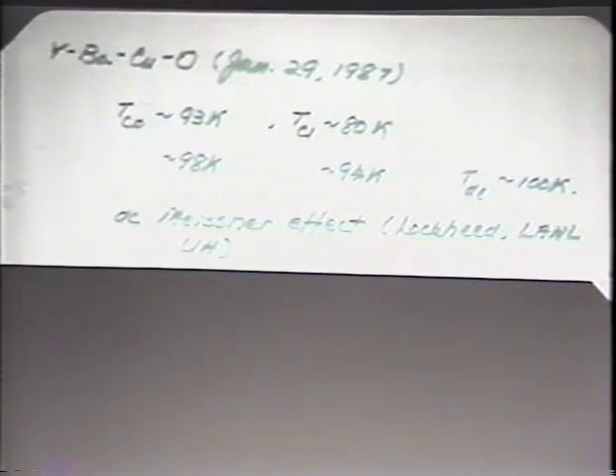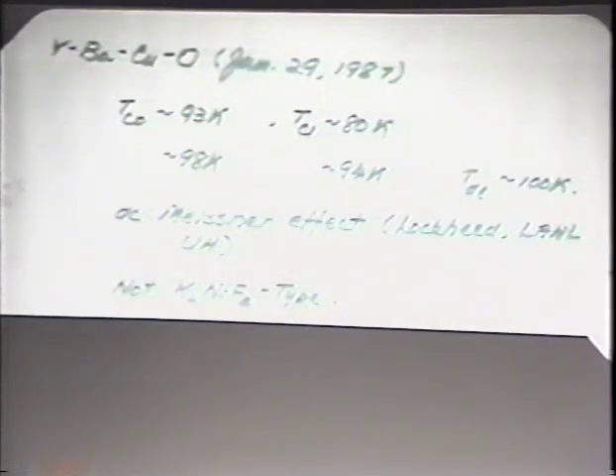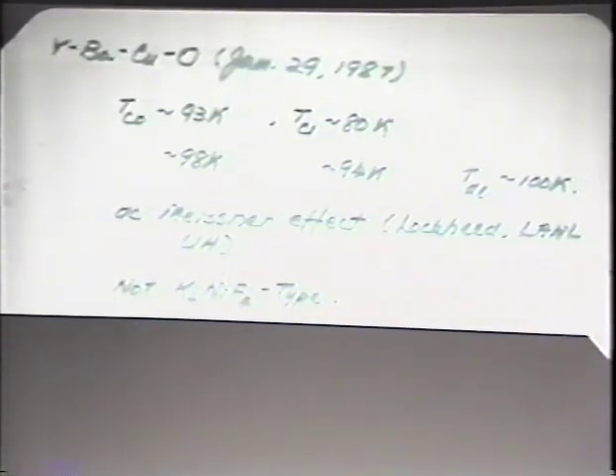By this time, we also went to measure the critical field, the Meissner effect, in fact, with the Los Alamos group and also Lockheed, C.Y. Huang and our group working together. That was the first time measuring the DC Meissner effect, confirming that this is indeed a superconducting transition. And also from our preliminary study, it shows that the characteristic of this material is different from the so-called layer structure.